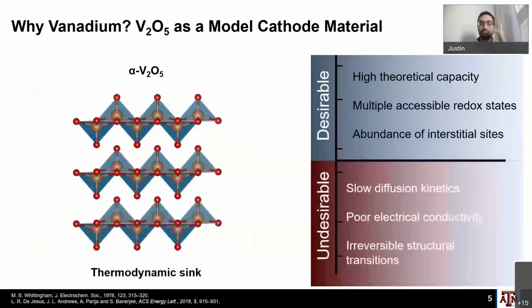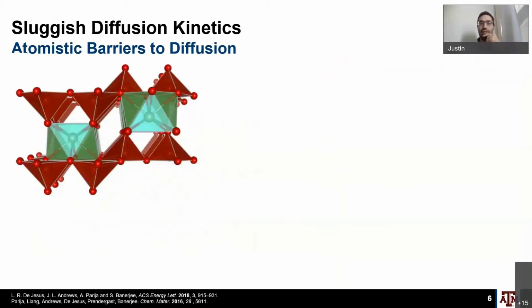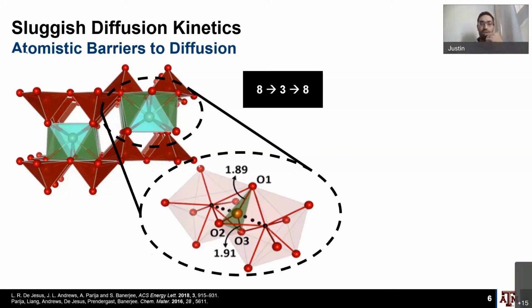And so what we've been interested in for a number of years, going back to before I joined the group and now even continuing on, is what are the fundamental origins of the poor performance of this material, and how do we improve its performance at an atomistic level and at the mesoscale in terms of the actual cell design and everything. So what it comes down to is that we have to consider all of the different barriers to diffusion. If we're thinking about why the diffusion of lithium ions is so sluggish in V2O5, there's an atomistic barrier to diffusion, right? And as lithium moves through the lattice, so this is some DFT results that Abhishek Parija from our group had pioneered.